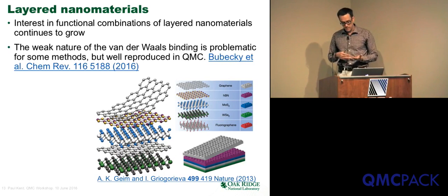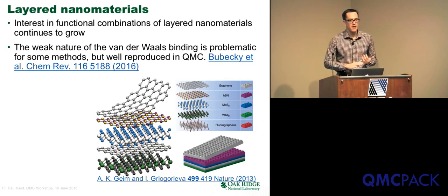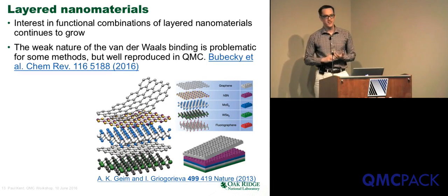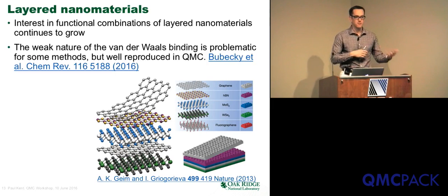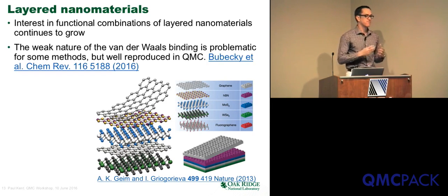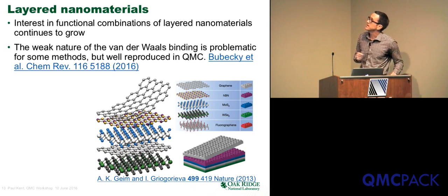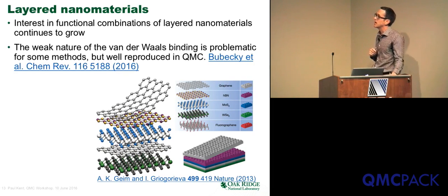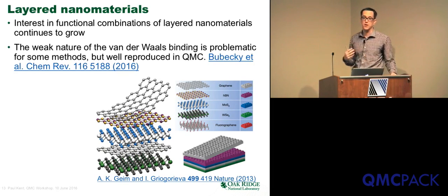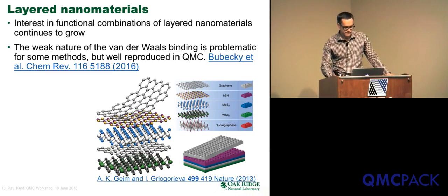Fundamentally, it's helpful that we have the full unapproximated Coulomb interaction, and I think David has a paper showing that the Jastrow actually essentially picks up van der Waals quite naturally. So there are fundamental reasons why we should be doing a good job of van der Waals materials. There's a nice review of this by Dobson and Mitas in Chemical Reviews, which also goes into solid state calculations as well, not only molecular calculations where they've done a lot of work.